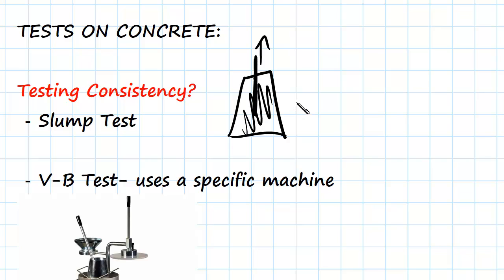And then what happens is we lift off the cone and step two is going to be that we're going to measure the slump. So we're going to be measuring this difference here. That's the thing that can be really just done on the work site with the concrete fresh. It gives a real-time, quite an accurate indication of the workability and the consistency of the concrete at hand.